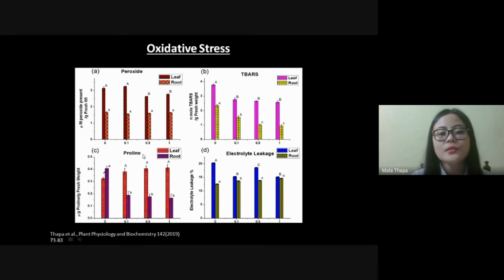Now, proline is also an important marker for plant stress management. We can see there is no significant alteration found in leaf proline content, whereas significant decrease found in root proline content, which again indicated the positive role of zinc sulfide nanoparticle. Now, electrolyte leakage. We have found significant increase in root electrolyte leakage. We can say that as roots were in direct contact with the nanoparticle, there may be a little increase in electrolyte leakage, but I'll explain it in my later slides.